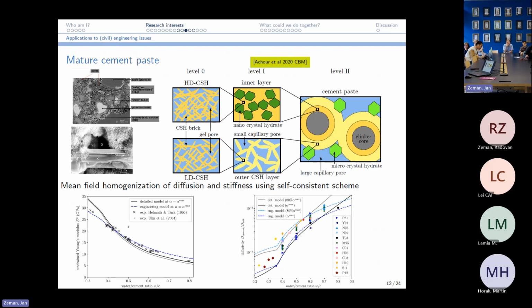which you can have from a hydration model, hydration of cement. And from that, we were able to see that for mature cement paste, which have been hydrated for more than 1 year, we can account for the decrease in Young modulus you would have when you increase the water to cement ratio at the mixing time, because you have more porosity. And in the meantime, when you increase the water to cement ratio, you have more porosity, and your diffusion coefficient increases about 1 to 2 orders of magnitude. What we can see is that the coefficient of diffusion in the cement paste is 3 orders of magnitude smaller than the one of ions in free water.